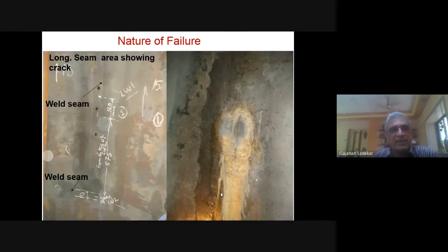Now, what happened is after 1.5 years, because it is a multi-wall and there's a venting system to test whether gas is leaking from inside, they observed that some gas is leaking. So the plant was stopped. Then after they removed the catalyst inside, we actually saw the surface. So this is the photograph.